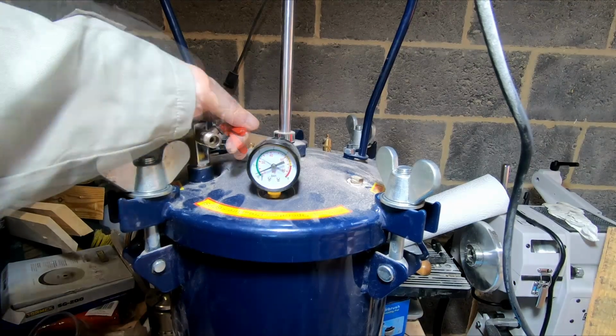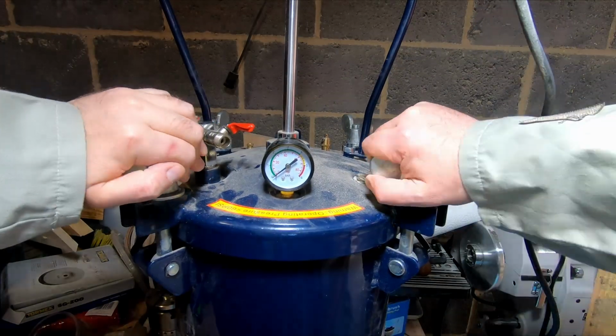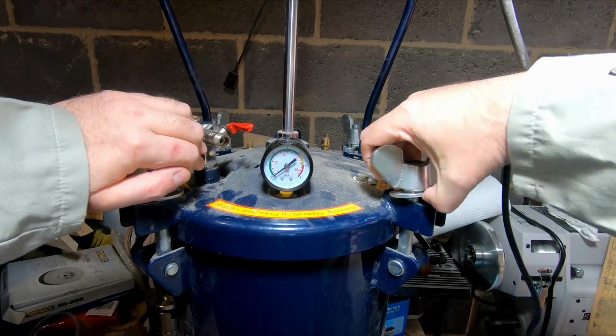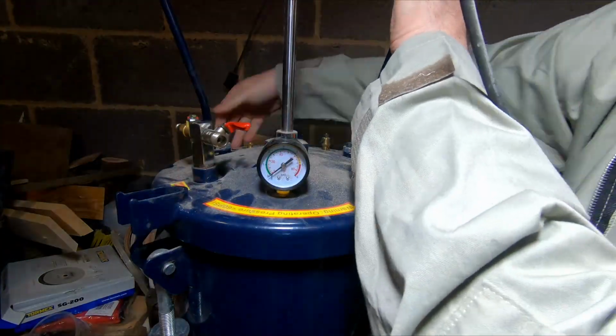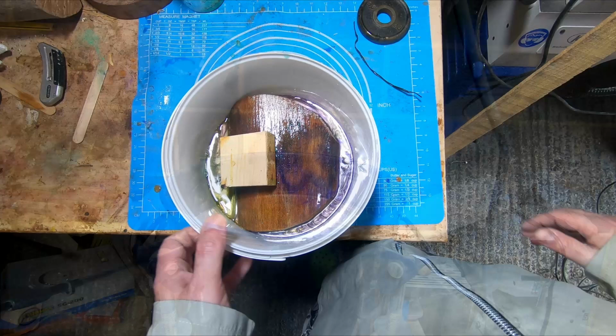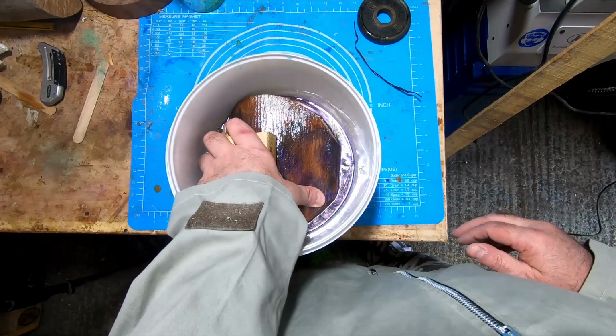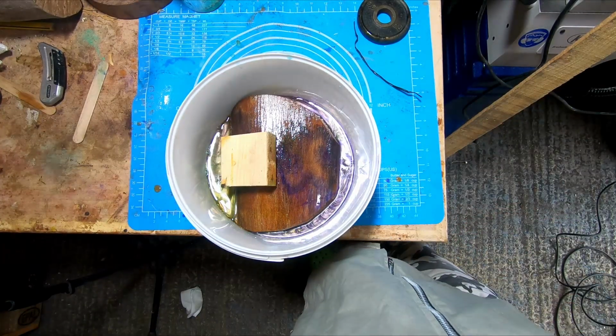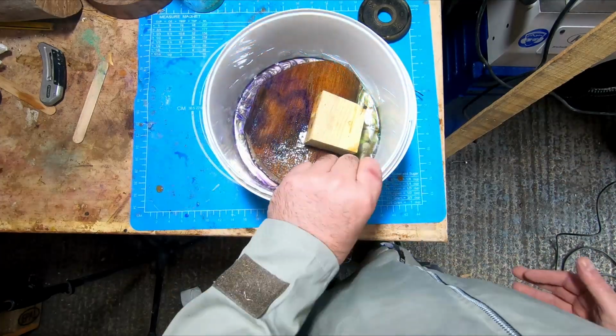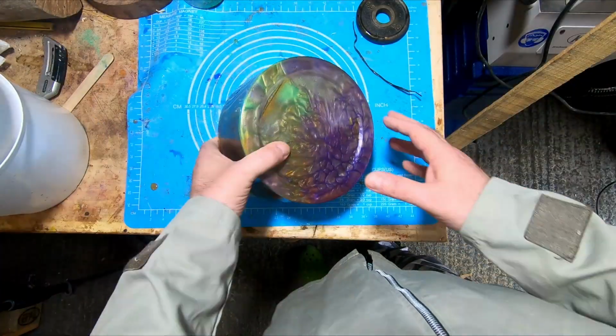It's been 24 hours and the blank has had plenty of time to cure. But as soon as I removed the lid, I saw a problem. In my haste to get the casting into the pressure pot, I had forgotten an important step. Although I had a small amount of weight on the blank, it was not enough, and the timber blank had floated up in the resin.